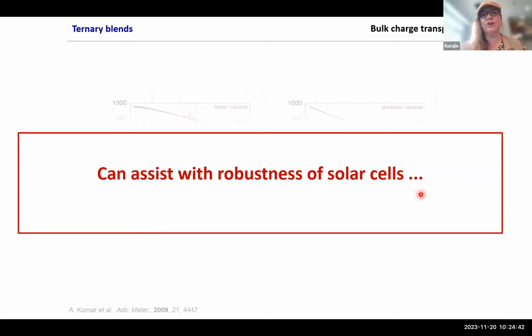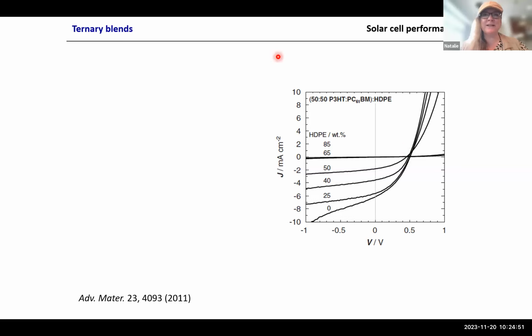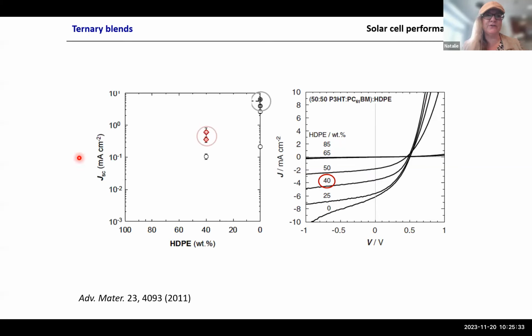And again, this starts to be important when we talk about robustness or durability, as we sometimes call it in specs. Here I have not our systems, but normal solar cells. You see the donor acceptor blend we used, this is pretty old work. So we had P3HT as the donor, a soluble fullerene acceptor, and then we added polyethylene. Here we have the current voltage characteristics, and let's first compare the blend, the binary P3HT PCBM, with one of the ternaries. And what is immediately clear, adding polyethylene doesn't absorb light, you lose on current, like the short circuit current. So if you plot the short circuit current, the blend and the ternary, well, it doesn't really look so good for the ternary. But again, if you have films of the same thickness, these systems absorb much less light.